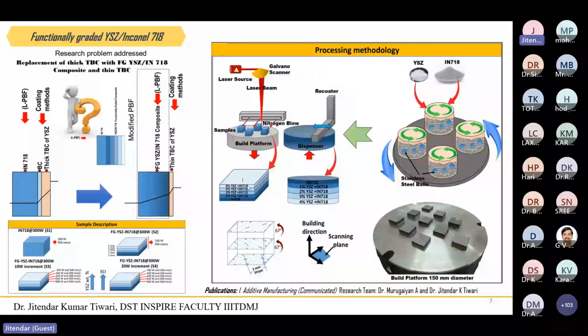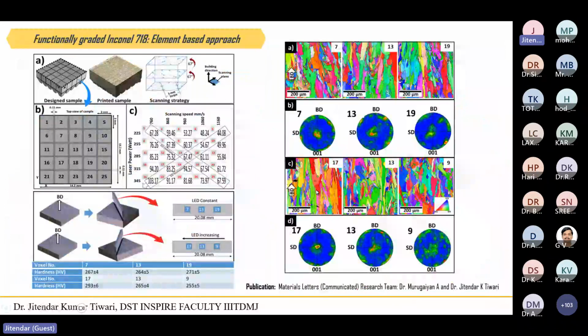So here I would like to mention in this slide, there is no material change, but the precipitation in Inconel 718, basically gamma prime and gamma double prime, is there. So the fraction of this gamma prime and gamma double prime can vary, and in most cases in the as-printed condition, I think there is a very low probability to form gamma prime or gamma double prime. But if the laser energy density is high, the precipitation time will be there, and it will get sufficient time to precipitate, and then this gamma prime and gamma double prime fraction can also increase.